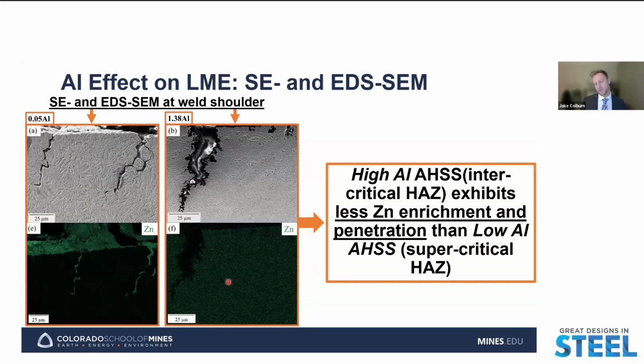But more than that, we also see that there's a difference in the zinc penetration and enrichment between these two alloys, where in the low aluminum alloy, we have, again, this noticeable zinc penetration and enrichment along and ahead of these LME cracks at the shoulder, whereas with the high aluminum alloy, there's really no noticeable zinc enrichment or penetration that we can detect here in EDS with the scan, to where any of this zinc contrast that we see here is just going to be background noise that's due to a difference in the counts per second that we're getting between the substrate and the mounting material here.